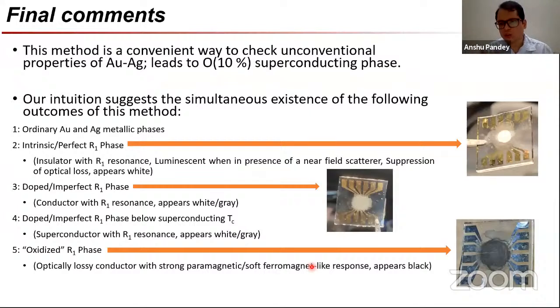If I had to comment on why this method, even though it seems so simple, is ultimately a problematic method, it is that it is not a way to get to pure gold silver, but rather, at least in our intuition, it seems to have around 10% of a phase which would give you superconductivity or superconductivity-like observations. As we understand it, and there's quite a bit of intuition here, but that's helpful in making materials at least. It seems as if this method gives rise to 5 possible outcomes, all happening within the same film. And depending on how the reaction is done in the precise conditions, you might get any of these 5 outcomes predominantly.